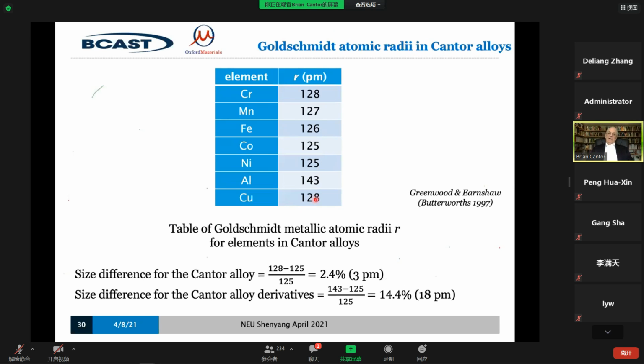Now let's look at the lattice strain. So in the Cantor alloy, chromium, manganese, iron, cobalt, nickel, these are the Goldschmidt radii. They range from 125 to 128 picometers, and the size difference is therefore about 3 picometers, about 2.5%. Now that's a big lattice strain. It's a very small distance, of course, even compared to the size of an atom, but it's a very big lattice strain. 2% strain in a material produces an enormous amount of strain energy and an enormous amount of local stress. That's why if you get much bigger deviations, the enthalpy of mixing becomes bigger and the solution breaks down.